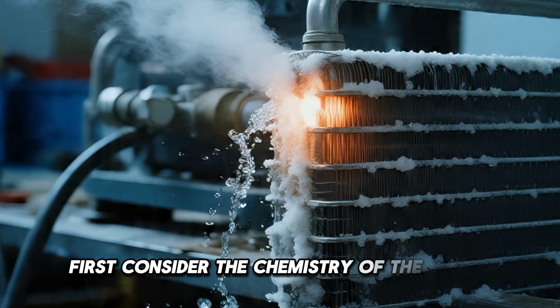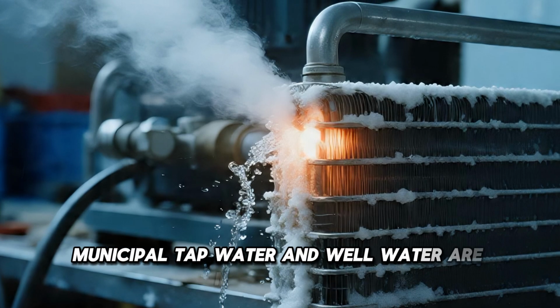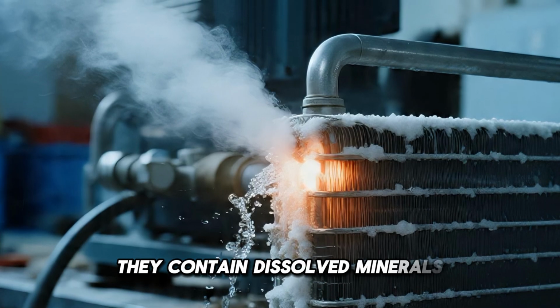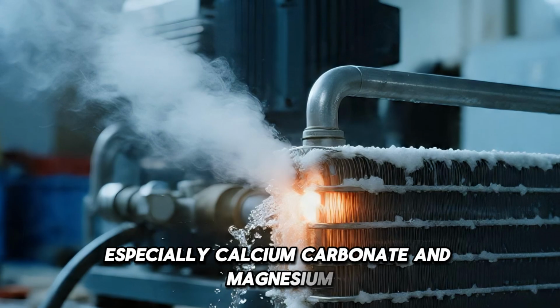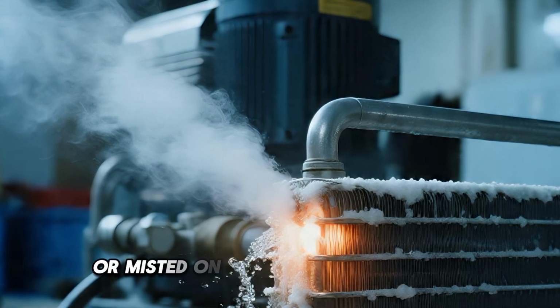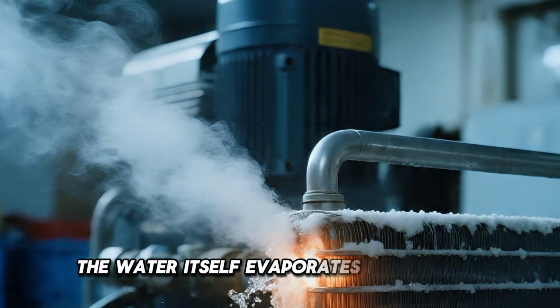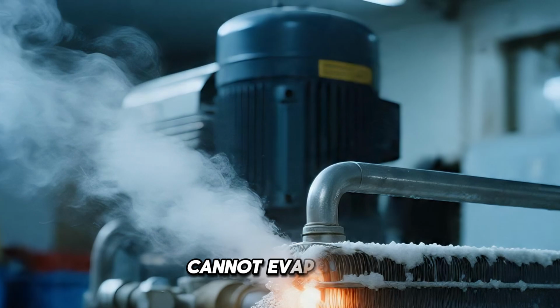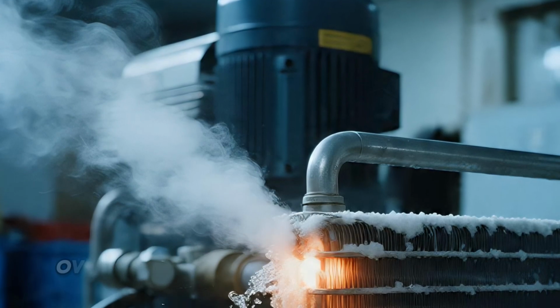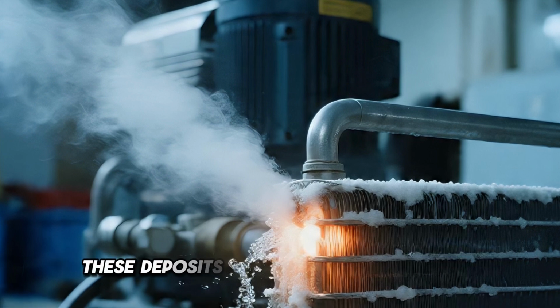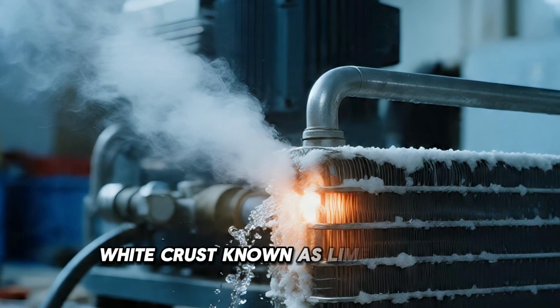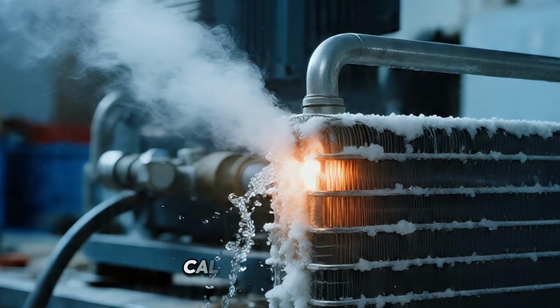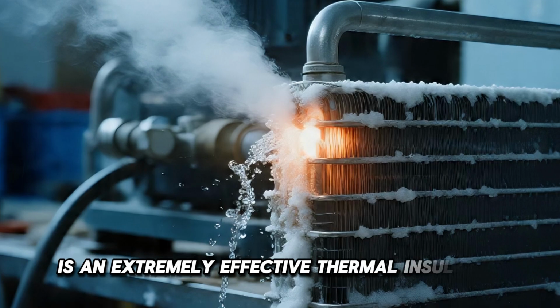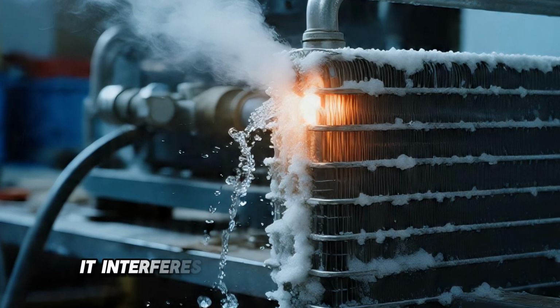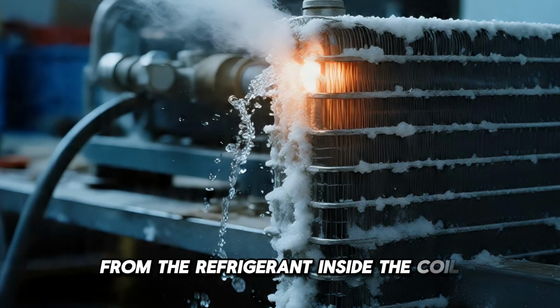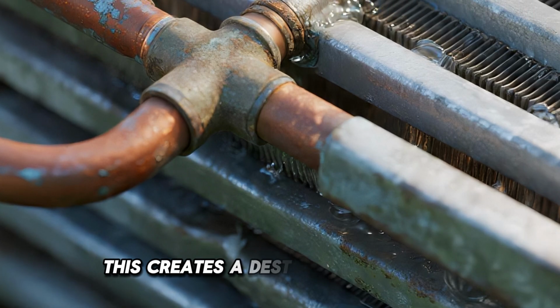First, consider the chemistry of the water. Municipal tap water and well water are not pure H2O. They contain dissolved minerals, especially calcium carbonate and magnesium. When untreated tap water is sprayed or misted onto a hot condenser coil, the water itself evaporates into the air. The minerals, however, cannot evaporate. They remain behind on the metal surface. Over the course of a single cooling season, these deposits can develop into a thick white crust known as limescale or calcification. Calcium carbonate is an extremely effective thermal insulator. Once it coats the condenser, it interferes with the movement of heat from the refrigerant inside the coil into the surrounding air.